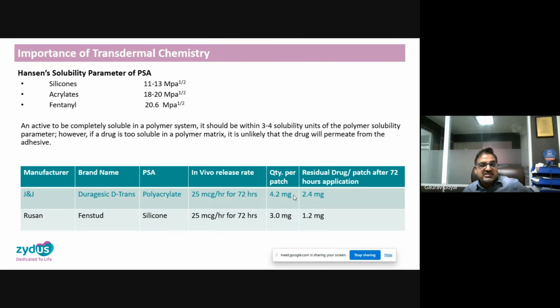So in one of the earlier slides, I told you the residual drug amount should be low. In the case of the Johnson and Johnson Duragesic patch, the residual drug amount after 3 days of application is 2.4 milligram, whereas in the case of Rusan, which we have developed, it is 1.2 milligram, which is almost half. So this is the important point to highlight. We can use different polymers to achieve a lower residual drug amount.